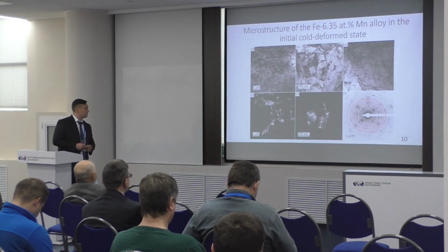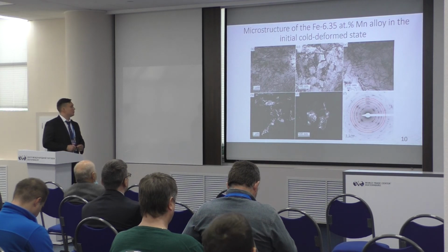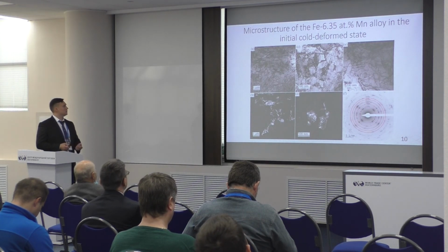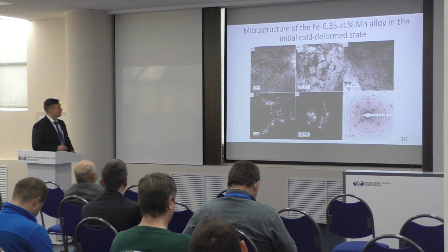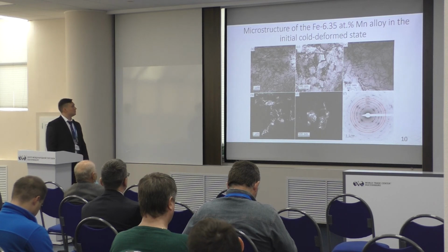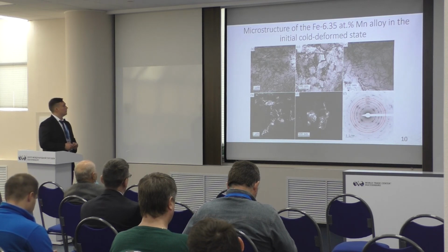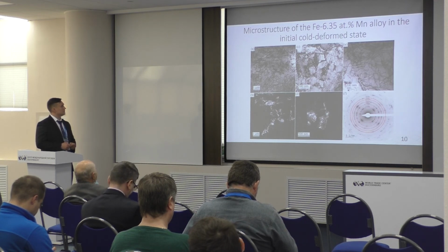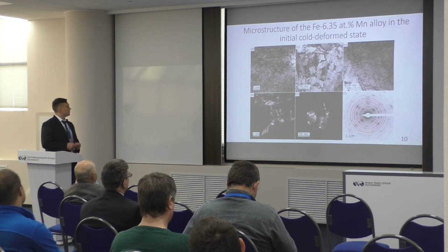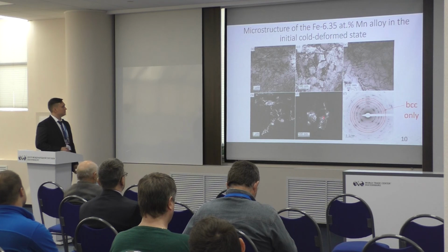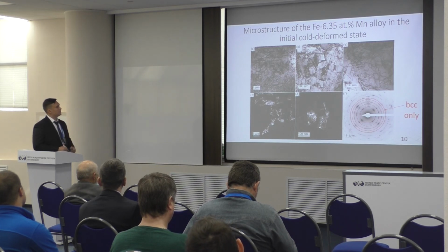And we confirmed our results of Mössbauer analysis using transmission electron microscopy. You can see the cellular structure of the initial specimen, cold deformed, and it is normal for the cold deformed state. There are the Bragg reflections of the BCC lattice of the alpha phase in this specimen.